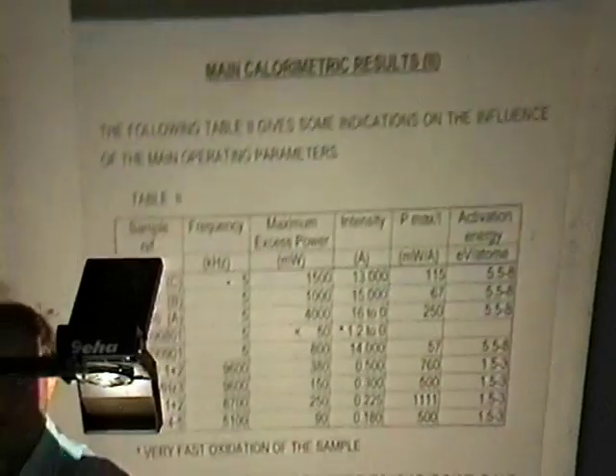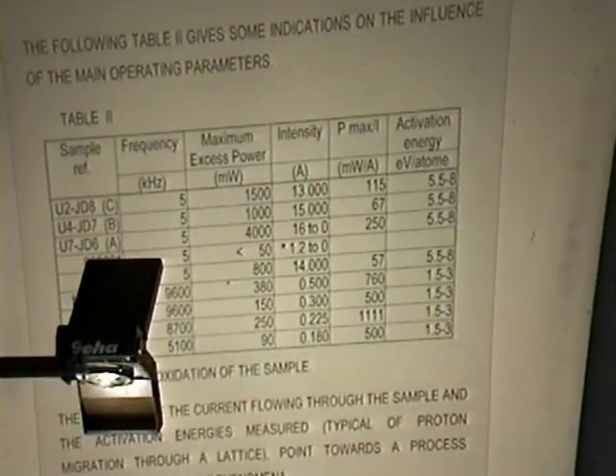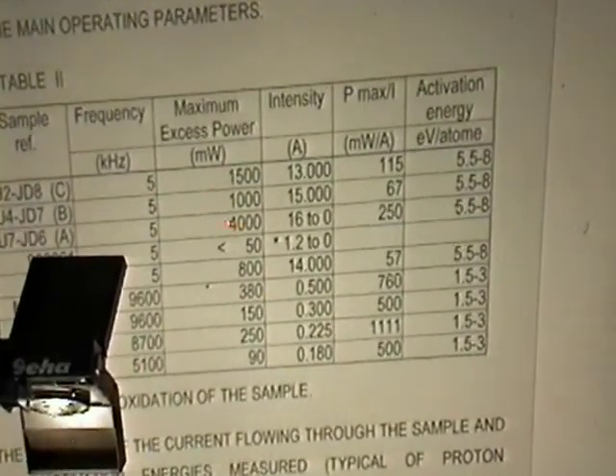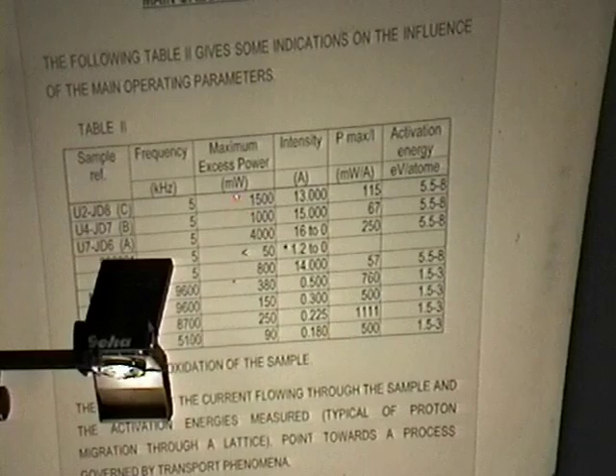So, in order to try to understand the origin of this excess of energy, first I will give you a brief effect of the operating condition of the experiment. The maximum excess power you can see range from 90 milliwatts to 1,500. This is the limit of detection of our method, which is not more precise than 50 milliwatts.